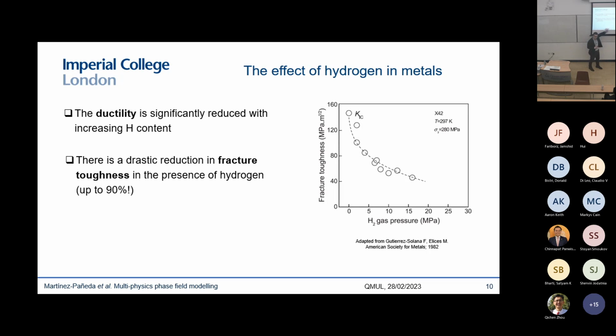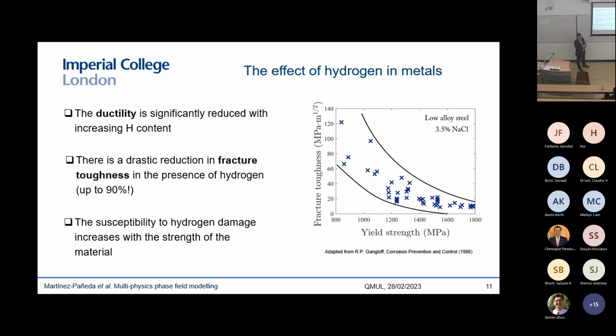And in high strength steels, the reduction in fracture toughness due to hydrogen can be of orders of magnitude. And I think this is a key point to emphasize, the fact that modern high strength steels are particularly susceptible to this hydrogen embrittlement phenomenon. And you can see this here. This is a plot of fracture toughness versus material strength, and this is for a given hydrogen content. So this is representative of seawater. And you can see that these modern high strength steels over here have fracture toughness in the presence of hydrogen that are below 10 megapascals root meter. So almost as brittle as ceramics.